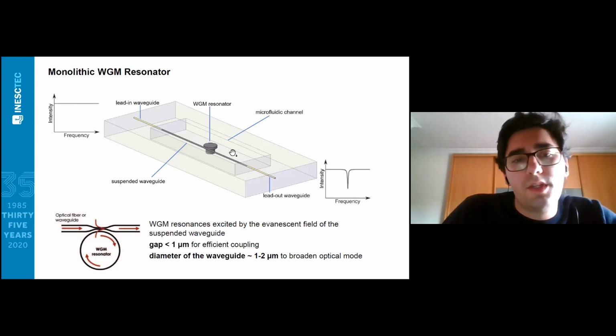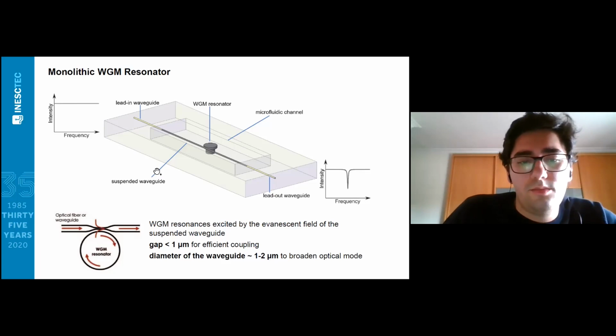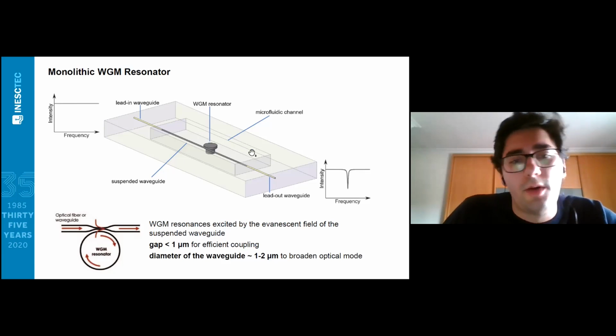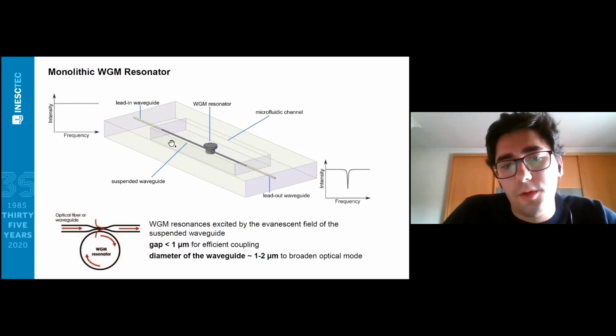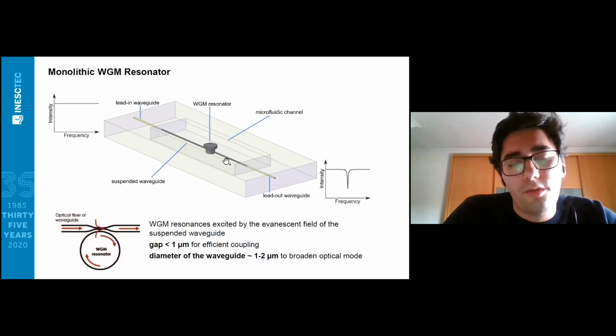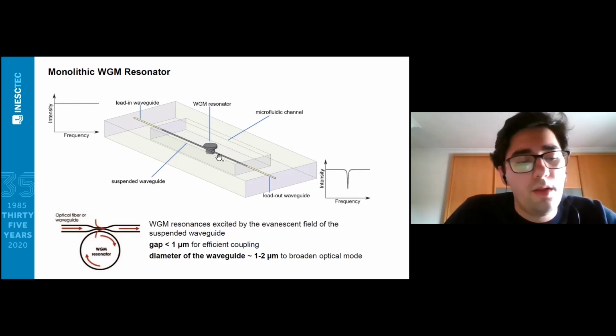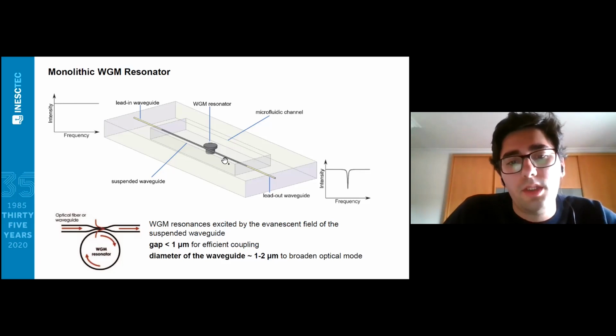So the fabrication of this device is similar to what we have discussed so far. We first perform femtosecond laser direct writing to machine the microfluidic channel. We then perform chemical etching to expose the microdisc and the suspended waveguide. We do thermal annealing to decrease the surface roughness. And at last, we write the lead-in and the lead-out waveguides to access the suspended waveguide.